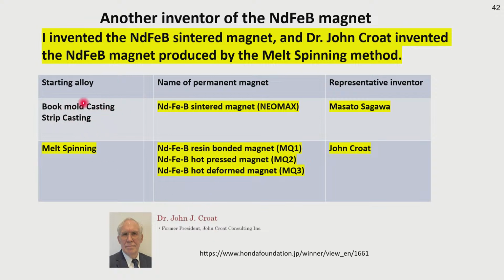We use ordinary casting to form alloys, but his method is using melt spinning, and by this method they can produce different types of permanent magnets: resin bonded magnet, hot pressed isotropic magnet, and hot deformed anisotropic magnet. And the typical representative inventor of this type of magnet is John Croat. And about the sintered type, myself.